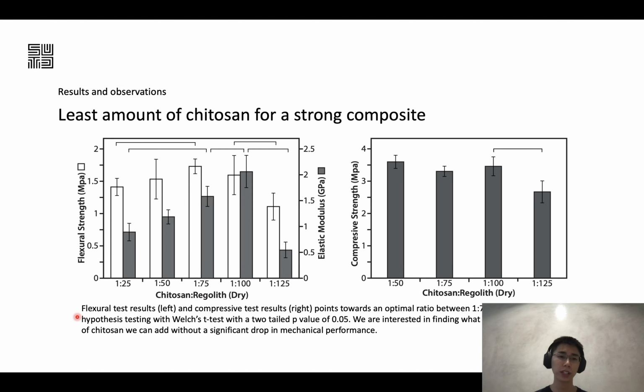Now, it's worth noting that at the ratio of 1 gram chitosan to 75 grams of regolith, this is actually a very low binder content as compared to some of the literature that I have come across, and actually to a notable literature that I have reviewed that noted itself to be ultra low binder content. This 1:75 mixing ratio is actually half of that.